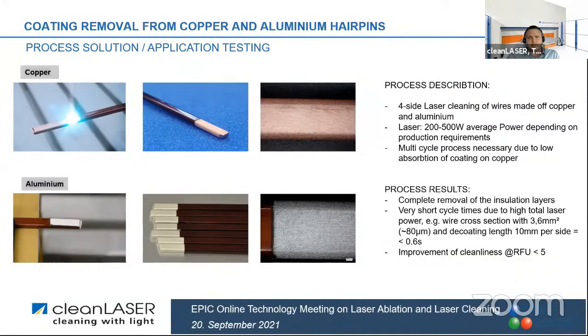One requirement is a measurement with the fluorescence measuring tool of a value smaller than 5. And this is possible with this kind of parameter setup technology. The speed varies and depends for sure on the layer thickness you have to remove and also the kind of plastics. A typical case is copper coated with a polyamide, 80 to 90 micron layer thickness, and the length of 10 millimeter, which you have to decoat, can be processed in less than 0.6 seconds.